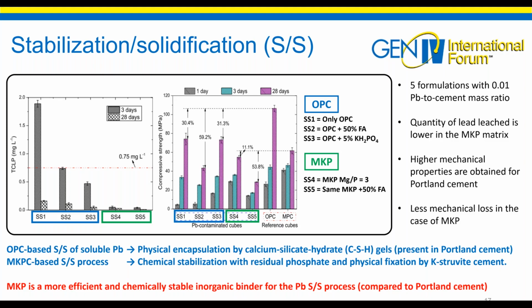From these two figures, it can be noted that in the case of Portland matrices, there is a physical integration of lead, whereas in the phosphate cement, we have a chemical integration of lead. Thus, for lead stabilization solidification, the use of phosphate matrix is preferable. Why do we have this difference between these two cementitious materials?